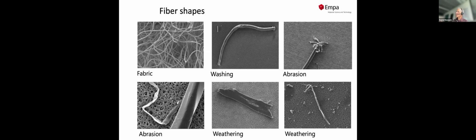and then you form some very thin fibers. And if you expose it to weathering, there are a lot of other particles that can then be formed just from the textile. So just looking at this UV weathering, there's a huge zoo of particles that is formed when textiles, polyester textiles, are exposed to sunlight. So what is released sometimes are these regular microplastic fibers, those that everybody studies. Then there are several that are in the process of splitting up. You see a lot of different forms here, a lot of thin fibers that can be formed.